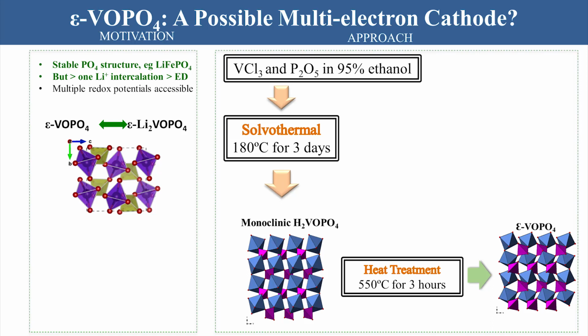With TiS2 and the layered oxides, you can't really do that. It's a nice 3-dimensional structure with tunnels in it, so it's very stable. It took us a while to make the material in what we call battery grade, where it would react with lithium. All phosphates are outstanding electronic insulators. So you've got to make it in a particle size in a manner where you can get those electrons to move. So we used a straight hydrothermal or solvothermal process, made this hydrogen intercalated material and fired it up to get the protons out. We can get the protons out in an electrochemical cell as well.